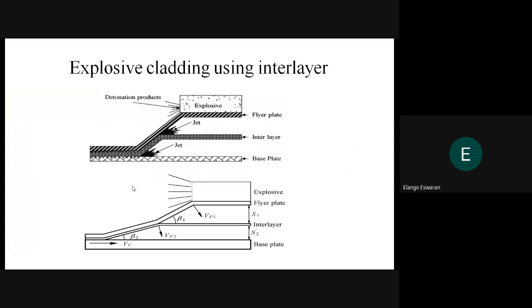The amount of kinetic energy spent at the interface dictates the formation of a smooth wave interface. As the process is very rapid, that is within a few microseconds, the judicious selection of process parameters, that is loading ratio, standoff distance, property of explosive and the flyer plate, etc., dictates the kinetic energy spent at the interface and restricts the intermetallic compound formed. Okamoto et al. emphasized the significance of kinetic energy spent at the interface and deduced an empirical relation which depends largely on the flyer plate velocity and the mass of the partition metal.